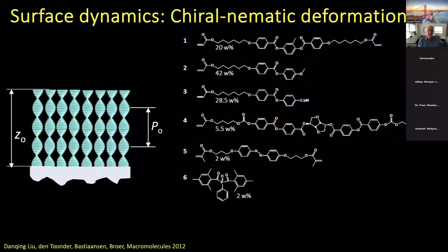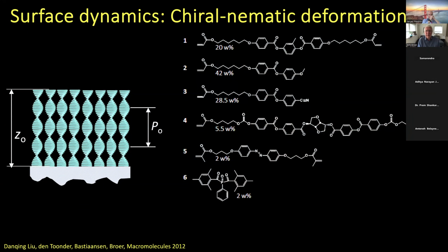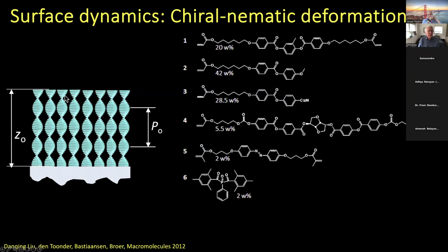So for that reason, we designed a blend which contains three basic elements. Of course, the liquid crystal monomer base, but we also added a chiral component to the system, and we added the azobenzene, and this is the photoinitiator to polymerize it. So you make a so-called chiral nematic polymer film where the molecules are forming a helicoidal structure with the helix axis perpendicular to the surface.